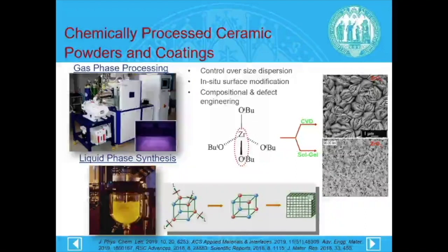The same chemistry can be used to identify certain breaking points where we have, for example, a preferential hydrolysis in the molecule to create an unsaturated metal coordination. So it promotes the molecular precursor, which is now partially hydrolyzed, to undergo a cross-condensation reaction, and this leads to the nucleation process, which is chemically controlled, something which is very well known for the sol-gel processing of nanopowders.